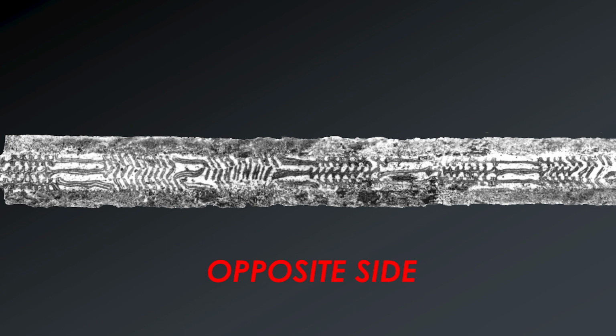On the opposite side, the first section is made of the same pattern as in the second section of the serpent side. The only difference is that the chevron straight pattern repeats 6 times instead of 4, and it runs half the length of the blade. Also note that it starts and ends with a chevron, missing the last straight laminate.